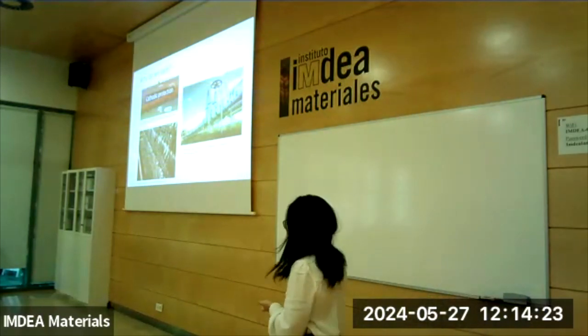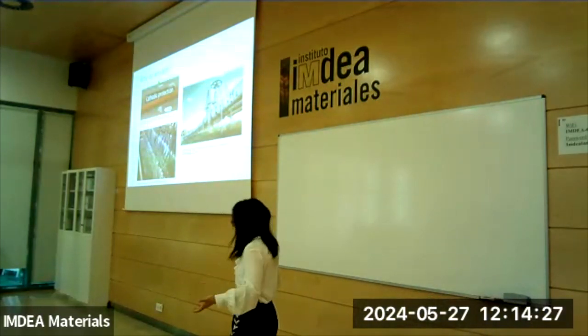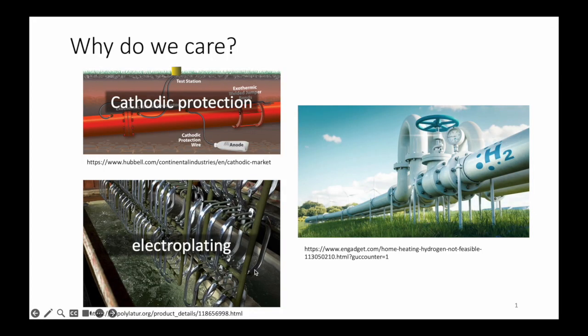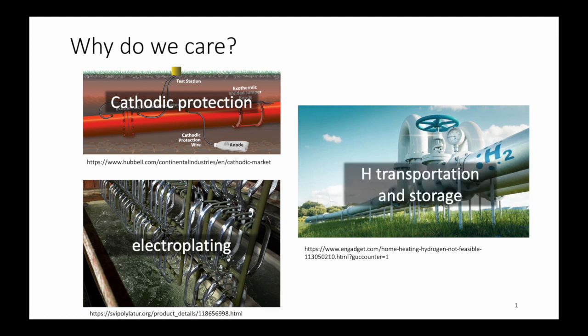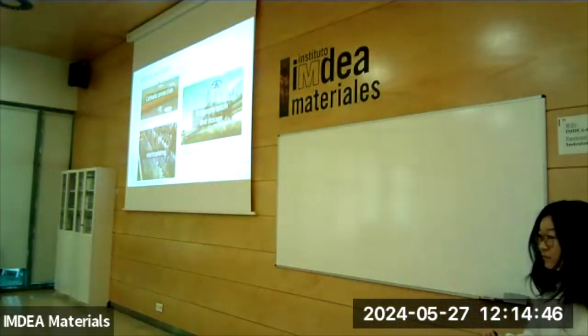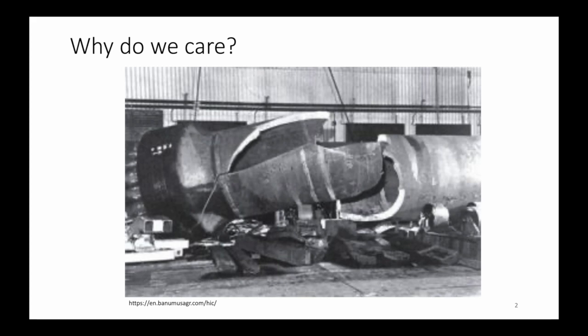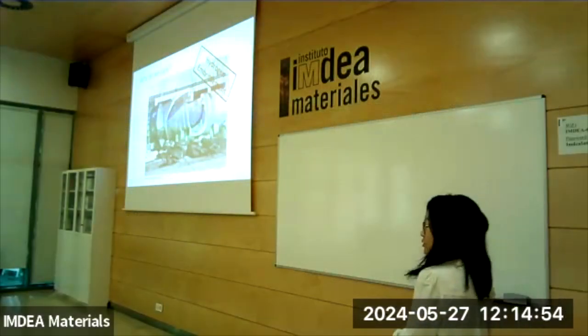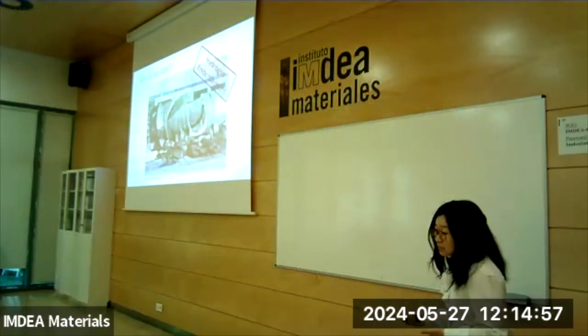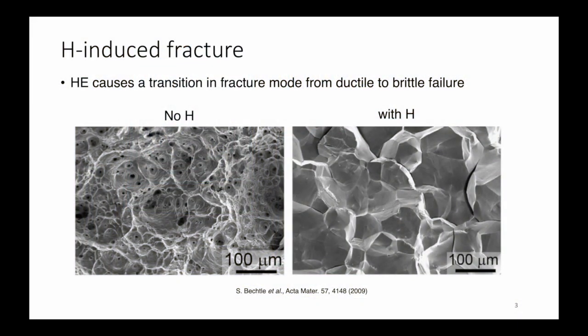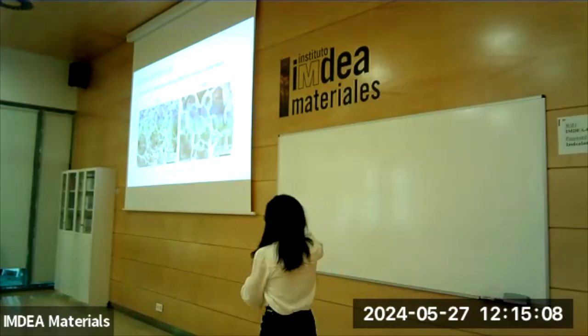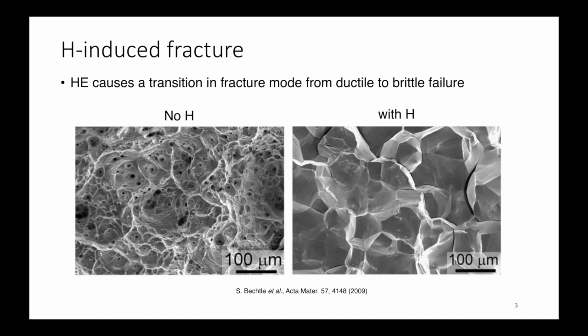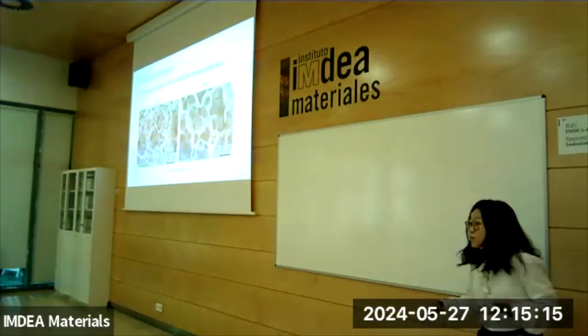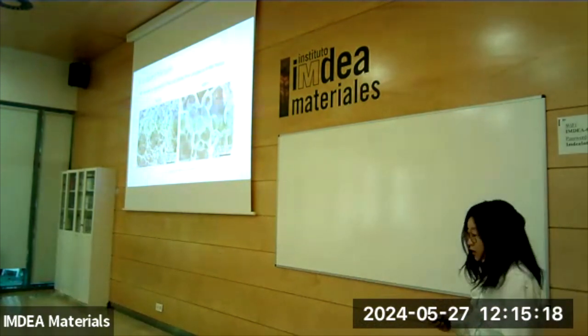In the second case, you can see here we are using electroplating. It's a similar idea. You get this material with a shiny finishing, but you also introduce it into a hydrogen environment. And the third one, as we said, hydrogen transportation and storage. Because these materials can be exposed to hydrogen, we definitely don't want this to happen. And this is hydrogen embrittlement. When a metallic material is exposed to the hydrogen environment, it loses its ductility and it becomes a brittle failure. Without hydrogen, you can see this is a ductile sort of failure, and with hydrogen, now we see this brittle failure.